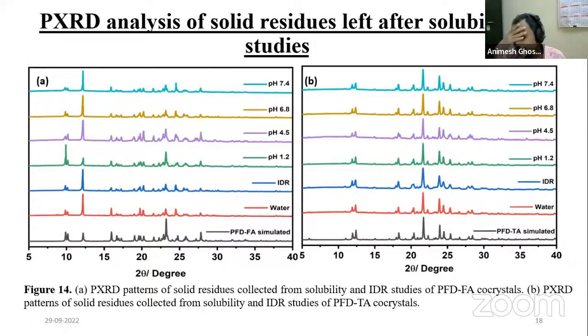Now, in any solubility study of a co-crystal, if you would like to check whether it is stable, metastable or unstable in solution, there is only one thing we can do: check in which form the residue is. So from the solubility study we collected the residue and went for the XRD data.